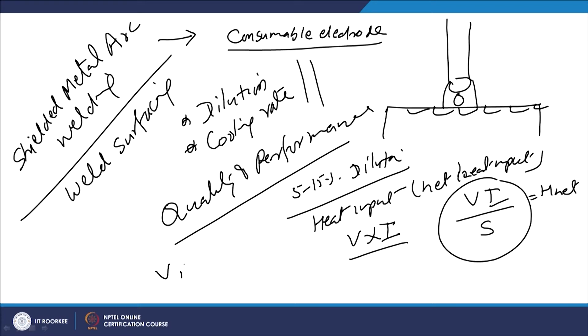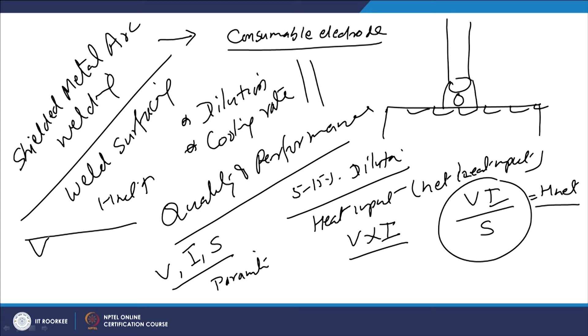Arc voltage, welding current, and welding speed are the three important welding parameters governing net heat input. H_net decides the depth up to which melting of the substrate takes place. In general, an increase in H_net increases the depth of melting, which in turn increases dilution. Increase in H_net also reduces the cooling rate. Both of these are undesirable. This general principle is applicable across all arc-based processes where heat is applied to develop a layer of required quality material over the substrate.